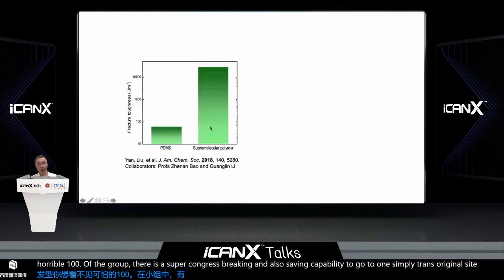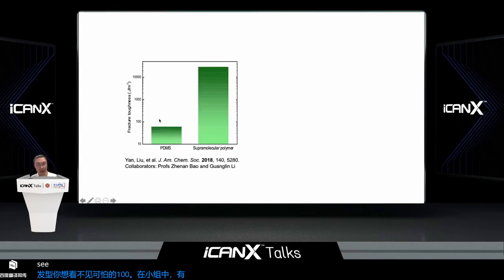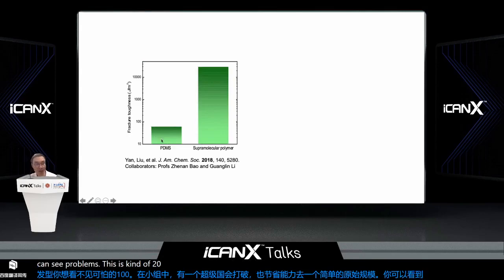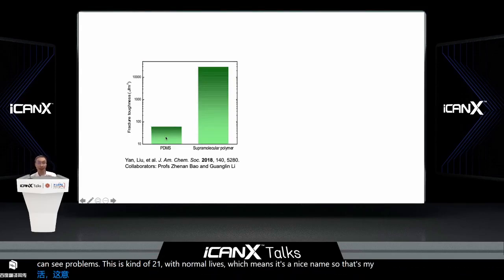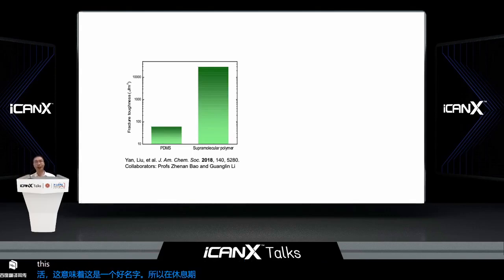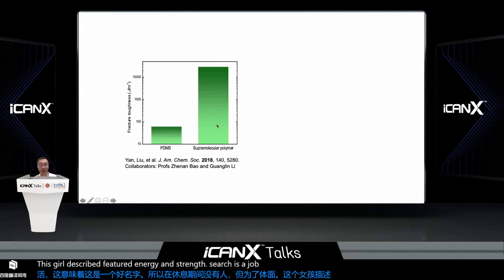And then we can look at the fracture toughness. PDMS is the kind of polymer we normally use. Its fracture toughness is less than 100, so it's no wonder PDMS easily breaks. But these supramolecular polymers have huge fracture energy, more than 30,000 joules per square meter. So this gives us the capability to develop anti-tearing electrodes.